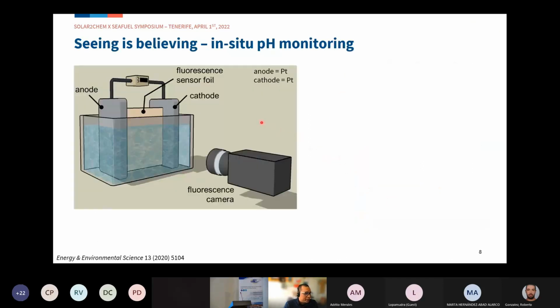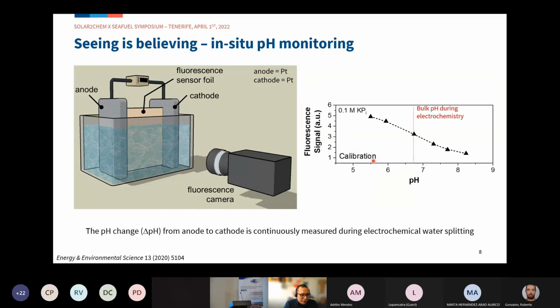To do that, we first did an experiment to monitor how severe the pH change happening really is. We did this with a simple experiment where we took a fluorescent sensor foil that is sensitive to pH and dipped it between the anode and the cathode, monitoring the fluorescence signal. This fluorescent sensor foil is sensitive between pH 5.5 and 8.5, which is ideal for our neutral electrolyte water splitting with bismuth vanadate. With this experiment, we continuously monitor the pH change between the anode and the cathode.